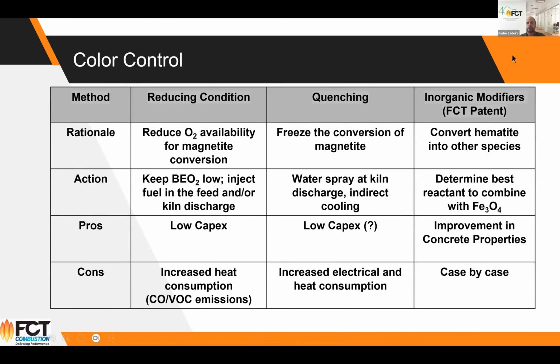And this would be the so-called FCT way. We have a patent for inorganic modifiers. So what are inorganic modifiers? Basically, what we're trying to do, once we have iron in the clay, is capture it and convert it into other species. So the action is to determine the best reactant to combine with Fe3O4 or Fe2O3 and to kidnap this form of iron. Well, the advantage is that it is typically followed by an improvement in the concrete properties of the calcined clay or LC3 cement. And the cons we can definitely discuss, but it's case by case.